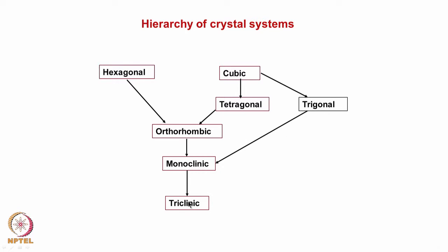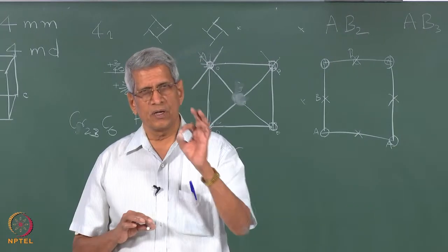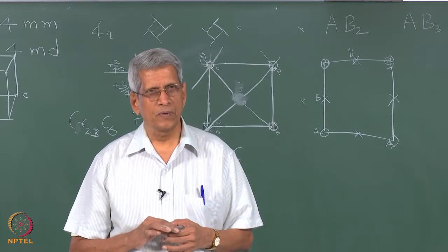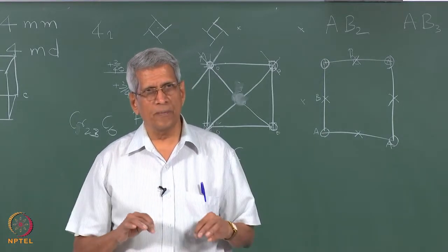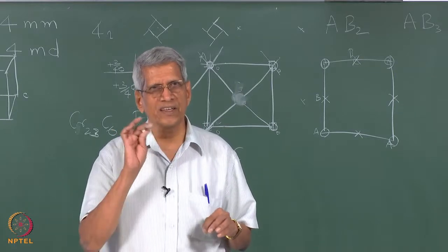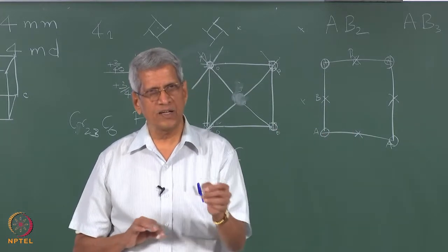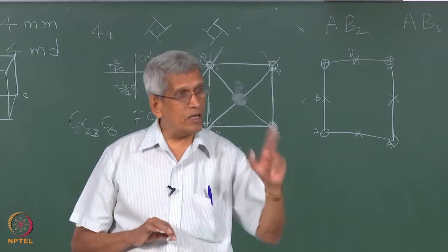So what is the transformation path when we do some heat treatment? What sort of crystal structures can it form during order-disorder transformation? This table essentially tells us that information. Suppose in an FCC material, an alloy, a hexagonal phase forms. From this you can make out that it is not possible directly. It can form only by introducing a defect in the FCC structure. You know that when a stacking fault is formed in FCC, it is nothing but the structure of HCP. That's the only way we can do it.